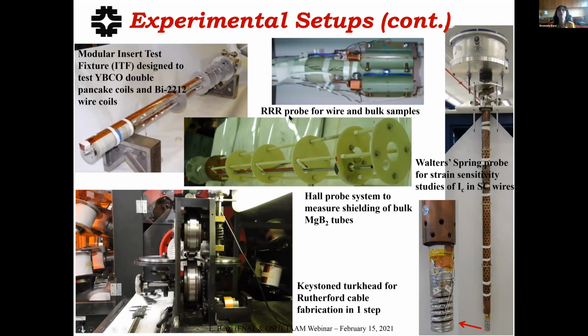in our lab. At some point we needed to test the shielding capabilities of magnesium diboride tubes. So we designed a very simple probe to house Hall probes to measure the fields inside and outside these tubes. This is the Turk head with which we make our Rutherford type cables. These are massive bulk machines, but this is actually very compact. It's one of the most compact machines in the world, so we can use it for R&D.